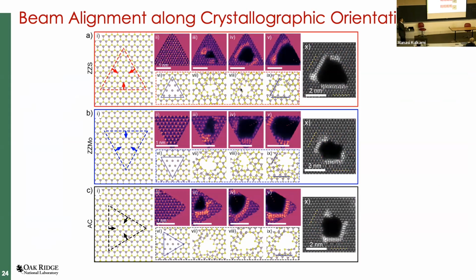If we're able to align the beam along certain crystallographic orientations, we can perhaps create structures with a high degree of fidelity. So this is what we did. We found that most of the reproducibility, we did a lot of these types of measurements for statistics, is basically if you did a triangular scan and then cut it along the zigzag orientation with the sulfur termination, moly termination, or even the armchair configurations. And you kind of see the armchairs right here.